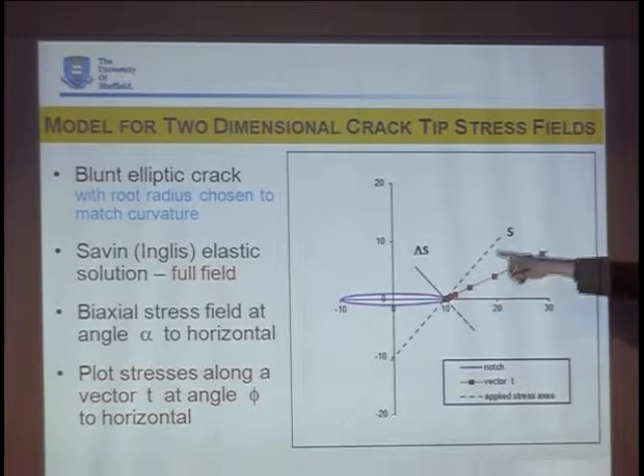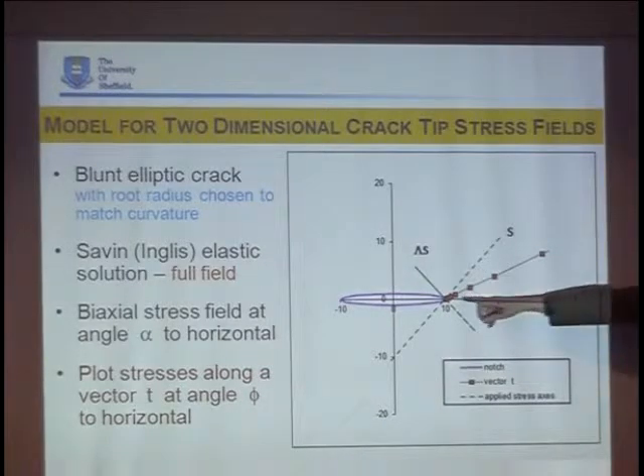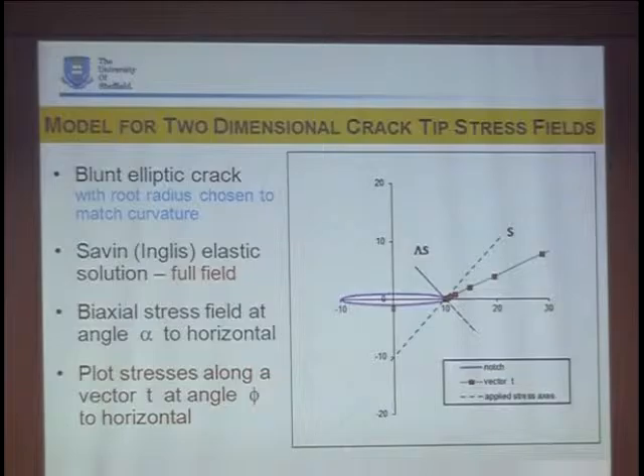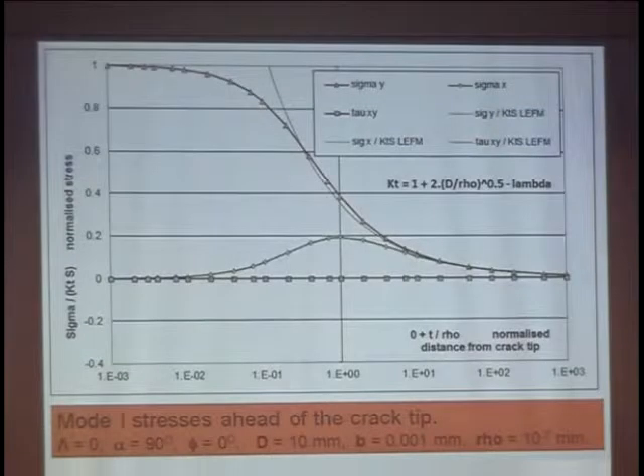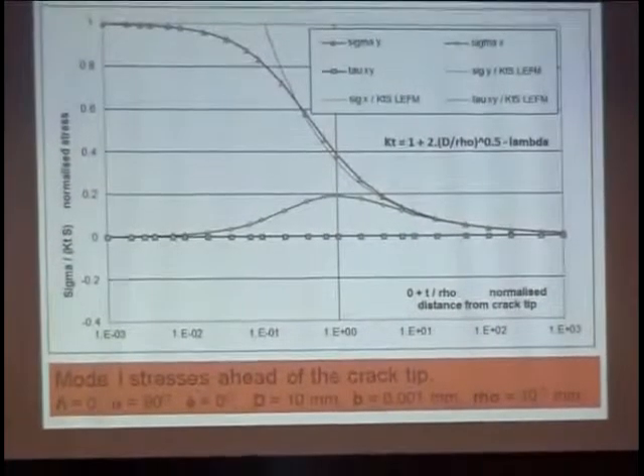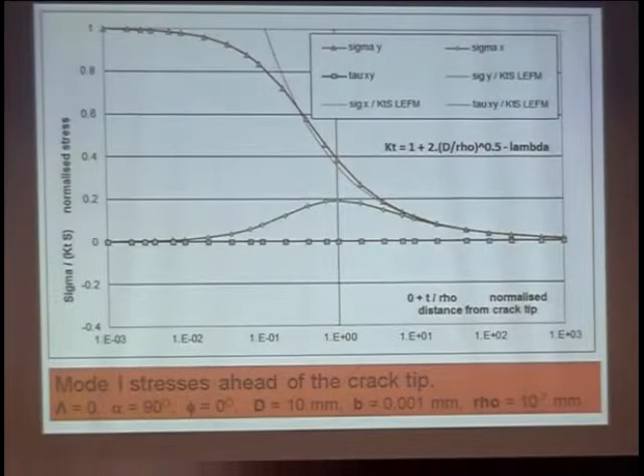To load this, we can apply stresses S and also lambda S at any angle alpha, so I have a completely general biaxial loading field that I can analyse through the Inglis method. This line here with the red points is just a vector taken from the root of the notch, and we can examine stresses along that vector at an angle phi to the horizontal and see what the stress field looks like. I'll start with mode 1 just to get you going and understanding what we're doing.